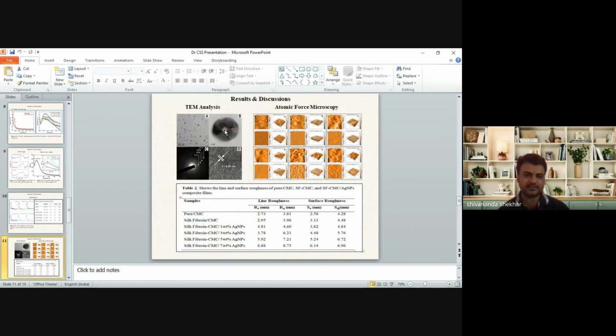In TEM analysis, we can see in the composite films the size distribution of nanoparticles present in figure A. And here, the single nanoparticles with a highly crystalline behavior. This shows that the formed nanoparticles have a face-centered cubic structure. Also, we have done the SAD pattern, the selected area electron diffraction pattern. We can get the different Miller planes, that is 111, 220, 200, 311. This confirms the formation of silver nanoparticles with a face-centered cubic structure.